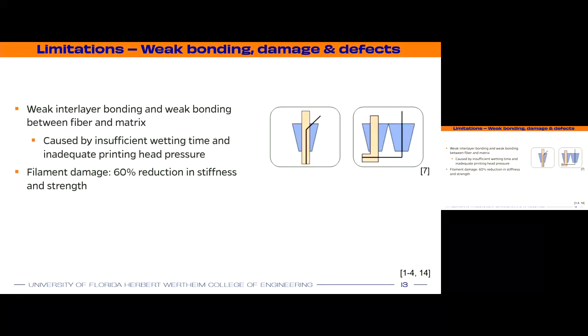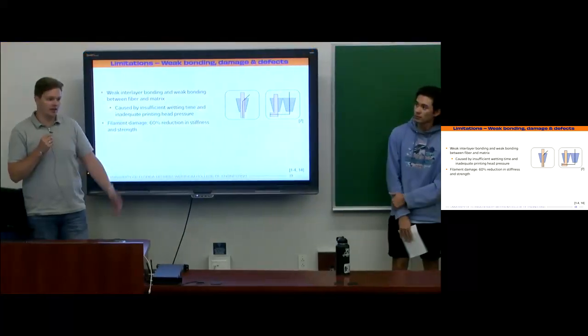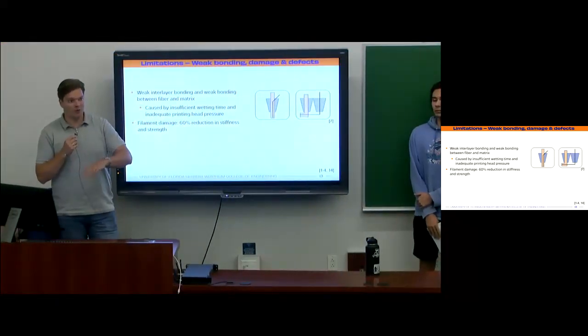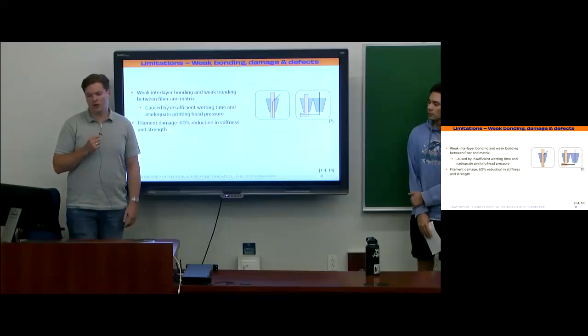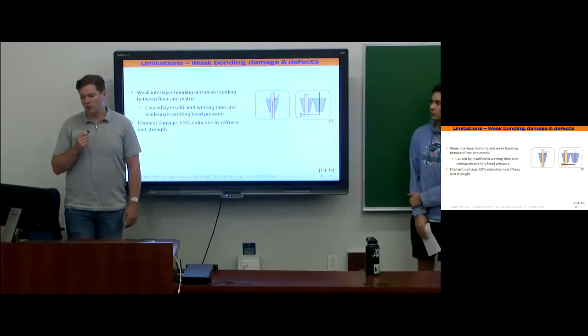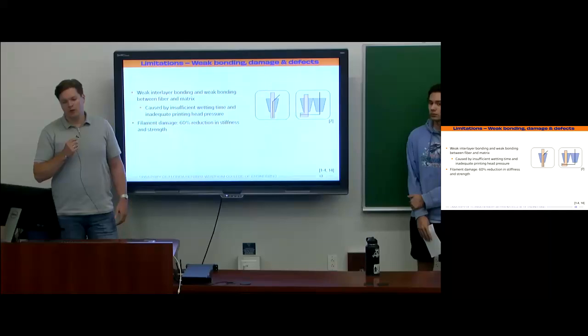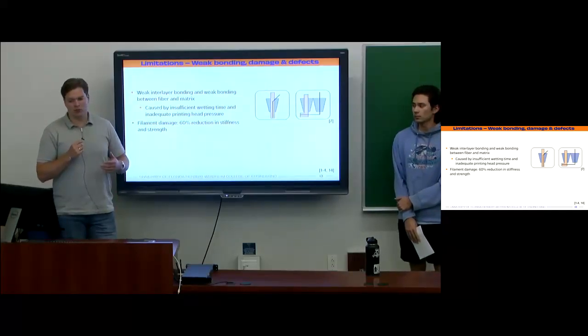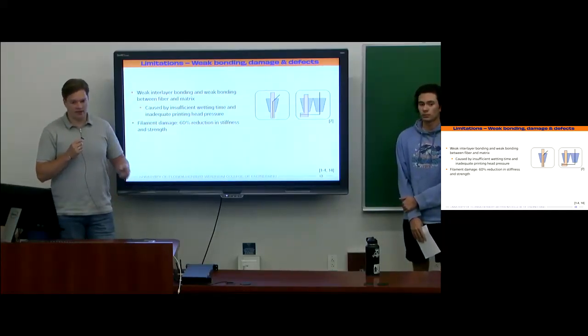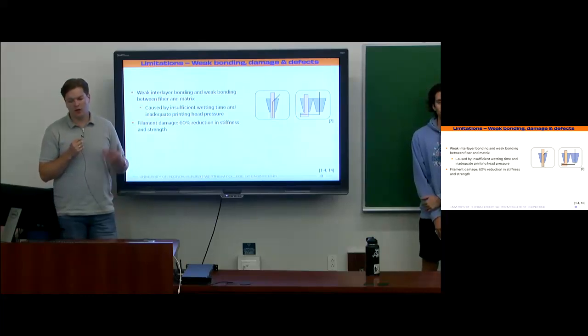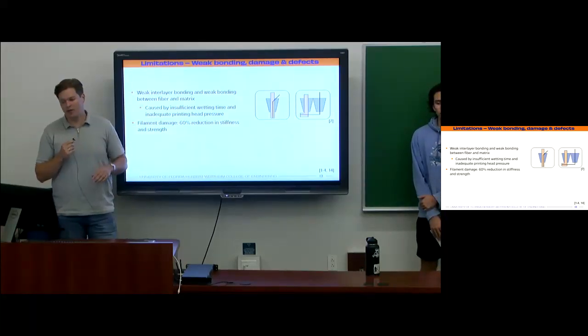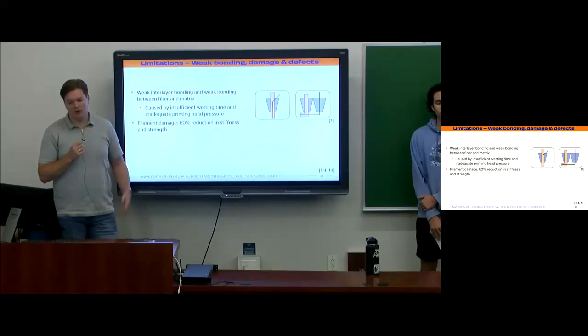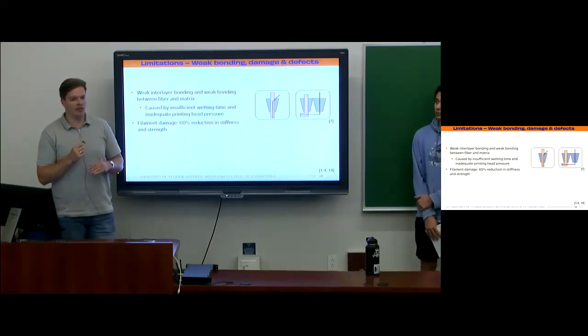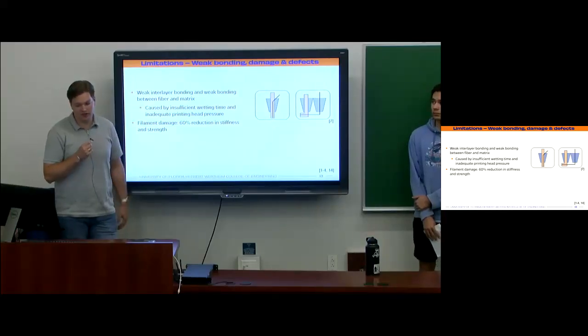Okay, so even though there are many advantages regarding the design freedom and the mechanical properties compared to the normal FDM process, there are certain limitations which mainly arise from weak bonding, damage, and defects. So weak interlayer bonding and weak bonding between fiber and matrix, so interlayer and intralayer bonding, are caused by insufficient wetting time during extrusion, and also a low printing head pressure, which is far lower than the pressures that can be reached in traditional processes.